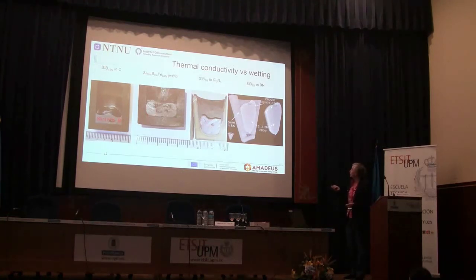Here we have a silicon boron alloy in a silicon nitride crucible, and we see it quite good. And here we have a boron nitride crucible with the silicon boron alloy, and we see that we even have a cavity of gas under here. This is a CT picture of the sample. So this is also something that needs to be taken into consideration. However, this is in small scale, and when you get to a bigger scale, will this be a problem? We really don't know yet.